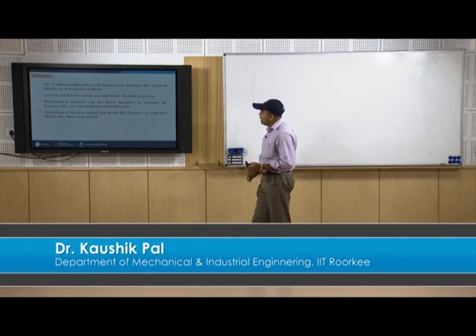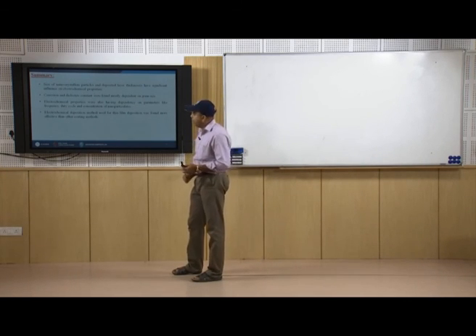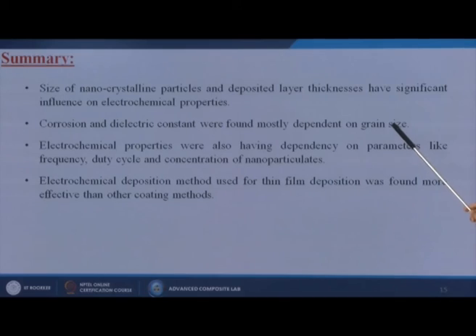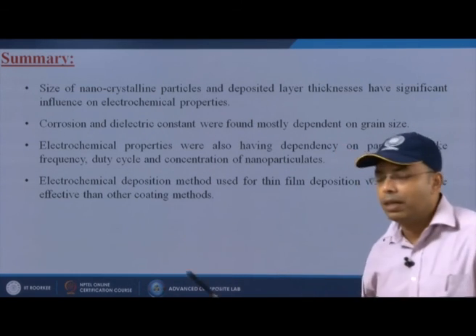Then we come to the summary of this lecture: the size of nanocrystalline particles and deposited layer thickness have significant influence on electrochemical properties. Corrosion and dielectric constant were found mostly dependent on grain size. Electrochemical properties also depend on parameters like frequency, duty cycle and concentration of nanoparticulates. The electrochemical deposition method used for thin film deposition was found more effective than other coating methods.